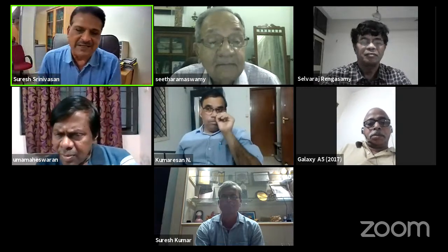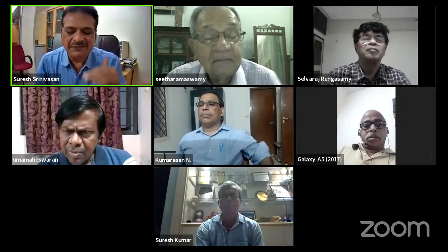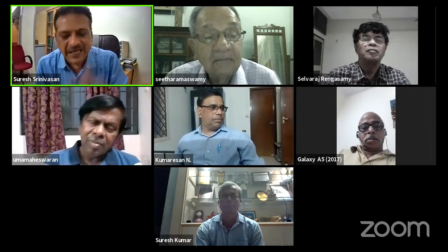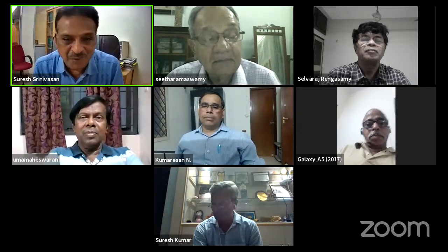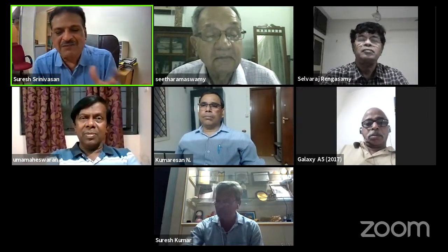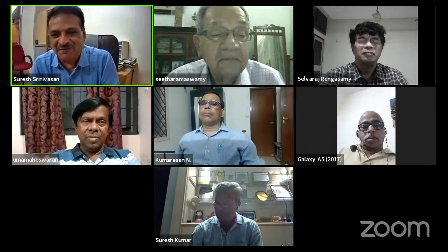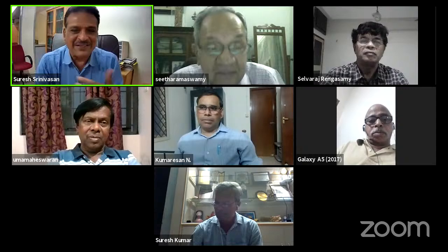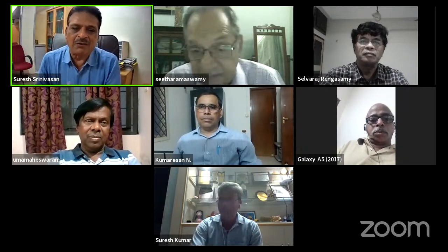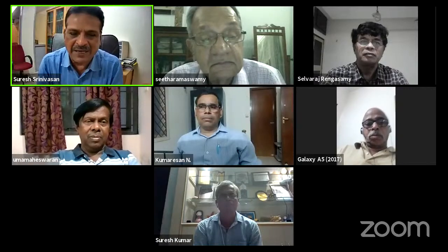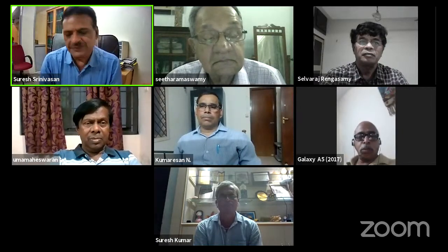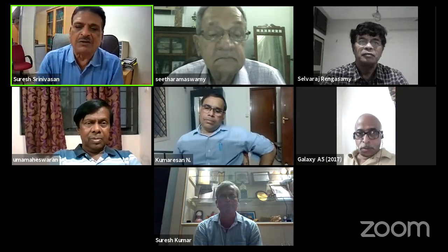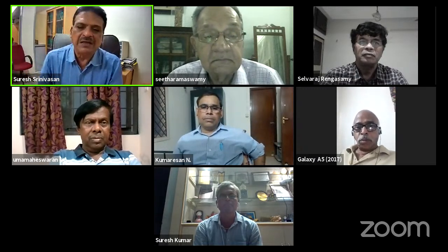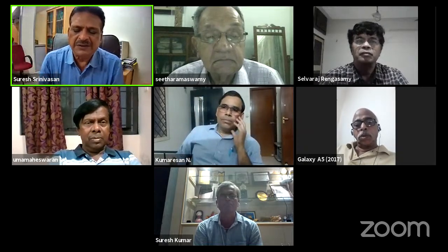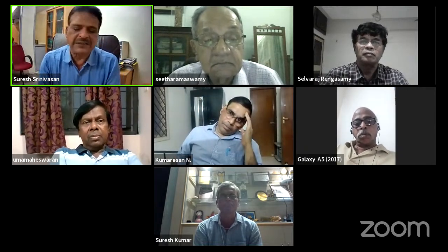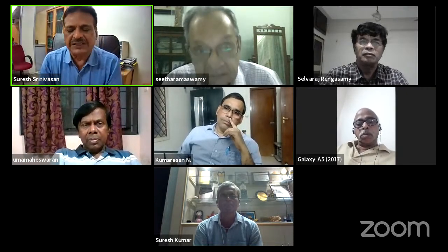Then we referred to BHEL. BHEL said that when the plates are above 2 inches, they have to be normalized and tempered; for smaller thicknesses, it is okay. So finally, after 6-7 months of negotiation, we zeroed in on Rourkela and Bhilai plant, if I'm right, to get these plates. A quality engineer was placed at the steel mill, who also measured the properties in longitudinal and transverse directions, as well as the grain size.